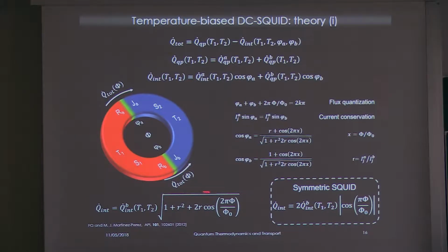and realize that the interference part has a shape that is identical in form to the expression for the electric critical current for a DC SQUID. Here r represents the imbalance between the two junctions. When the SQUID is symmetric, so when the junctions are identical, you obtain that the phase-dependent part of the heat current oscillates as the absolute value of the cosine, identically to the charge in a charged SQUID.